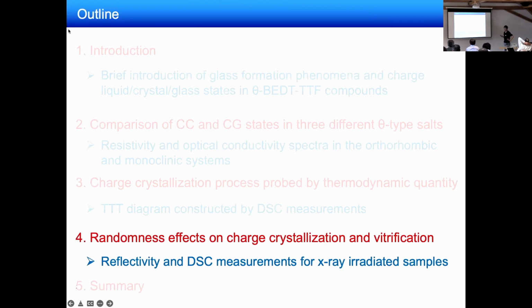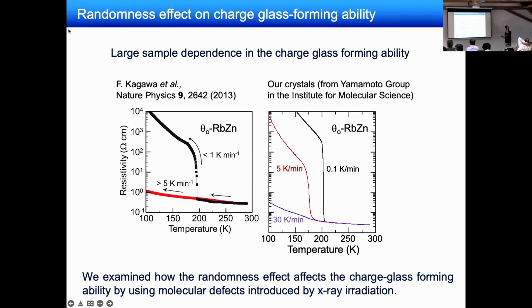Okay, so finally, I will talk about the randomness effect on charge crystallization and vitrification. Since organic materials are very clean, we expect that the charge glass formation is essentially free from disorder. But actually, we recognize that there is a large sample dependence in the charge glass forming ability. This is resistivity data of our rubidium zinc compound, which is provided by Yamamoto Group in Japan. In our case, the critical cooling rate is about 30 Kelvin per minute. But in the previous results, it was 5 Kelvin per minute. So this difference may come from the different sample qualities.